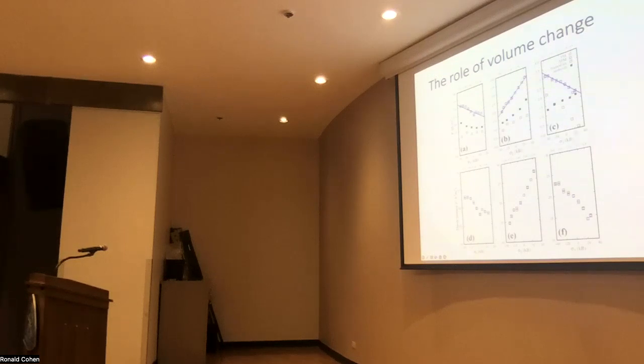To investigate that, we actually computed the response of the dipole moment to the applied stress. And as you can see from this blue data, the response of the dipole moment is very much correlated with the response of the polarization. So we don't believe that it is the volume that is responsible for the effect.